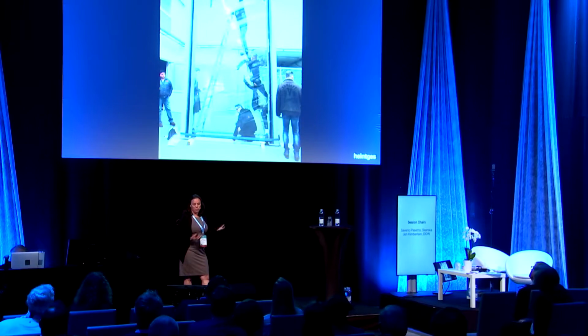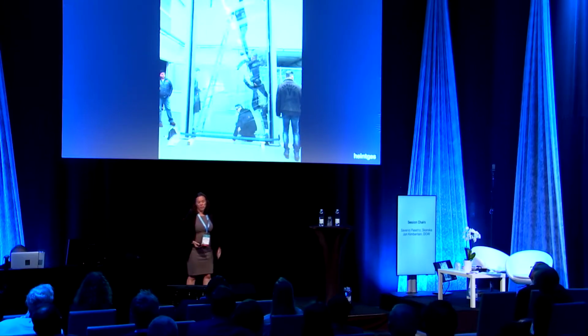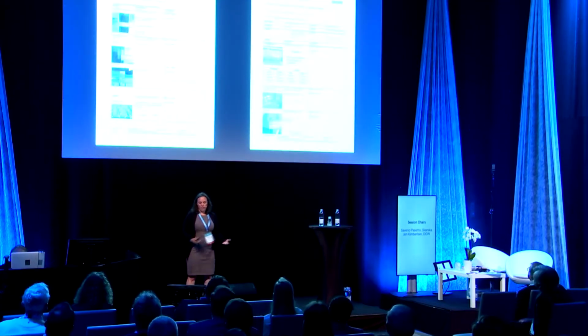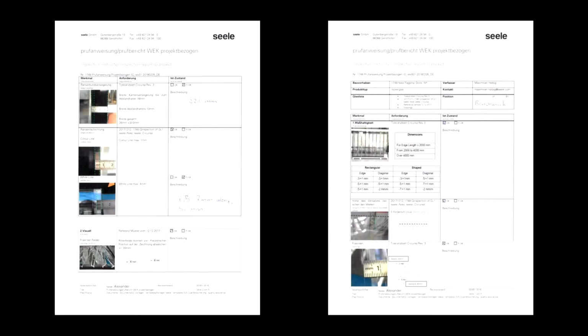An assembled IGU was also put in seele's facility and reviewed by the design and construction team to establish acceptable criteria for the quality control of the production glass. There was a QC inspection checklist established that seele used to check each completed IGU. The issue of the climatic loads and the airspace came up again here. In one of the early samples, there was damage caused when the inner and outer lights had touched, the airspace being too narrow in the middle. And fabrication methods were established to ensure that that gap was consistently wide enough.